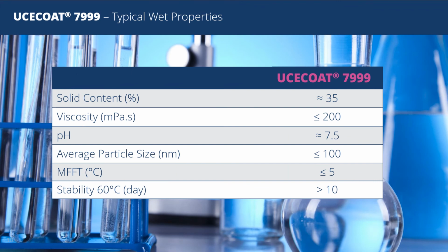Now, let's look at the wet product characteristics of UCECOAT 7999, summarized in the table. They do not provide any bad surprise. The solid content is about 35%, with a pH around 7.5 and a viscosity below 200 millipascal seconds. The mean particle size is typically below 100 nanometers and provides a good colloidal stability, which is above 10 days at 60 degrees. The minimum film formation temperature is below 5 degrees.